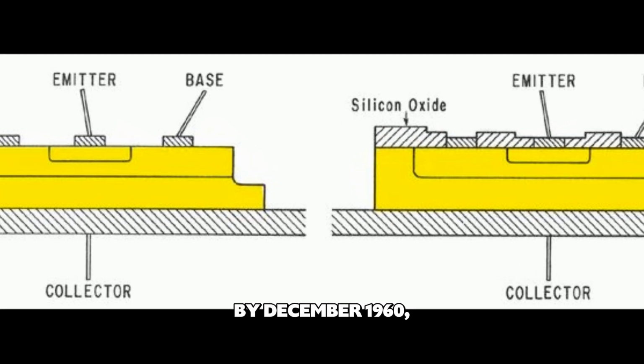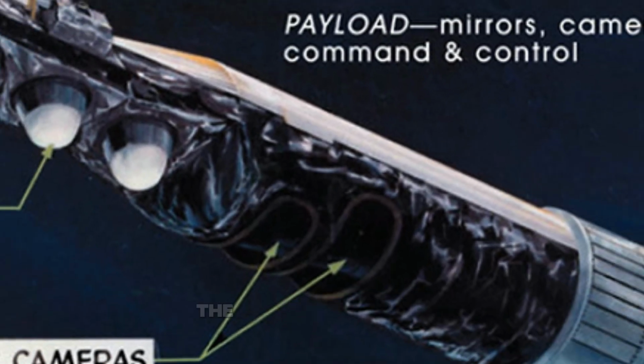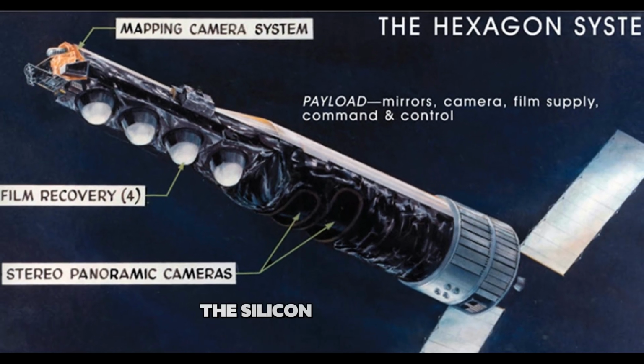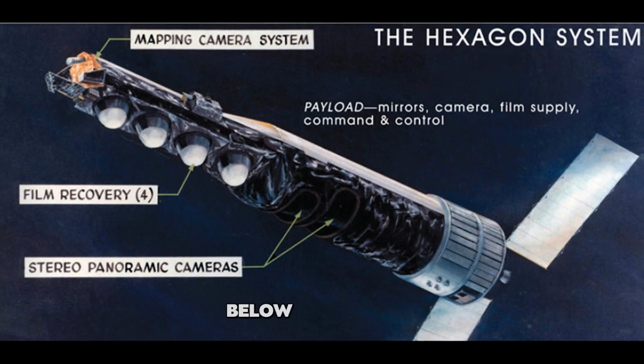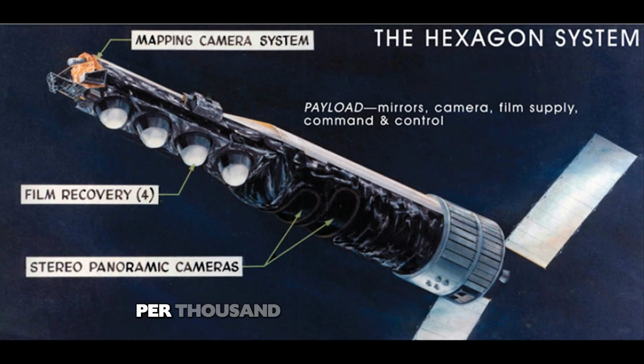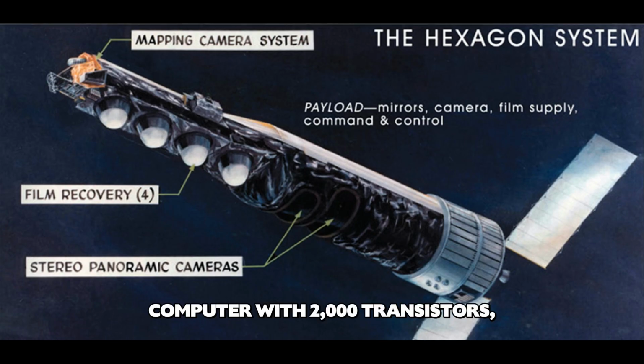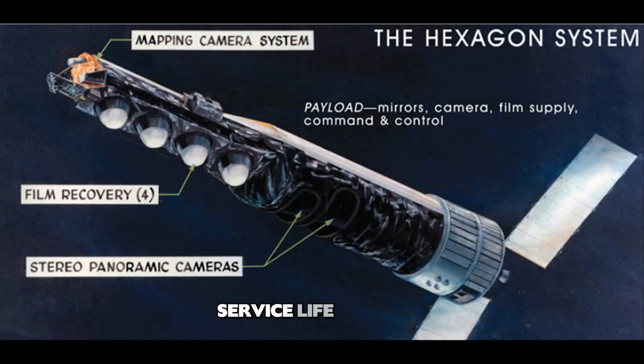By December 1960, Autonetics had the data the Air Force demanded. The silicon transistors showed failure rates below 0.01% per 1,000 hours, meaning that in a guidance computer with 2,000 transistors, the probability of any single transistor failing during a 10-year service life was less than 2%. With modest redundancy designed into the computer architecture, reliability exceeded 99.8%. This was better than any electronic system ever deployed in a military application.